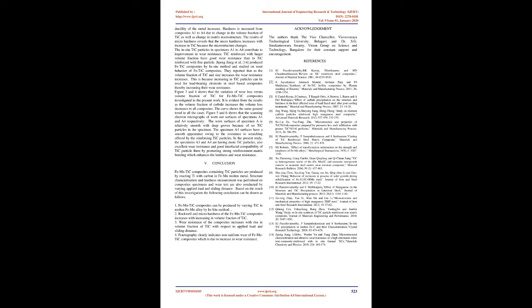In the present study, the specimens A3 and A4 have more TiC particles, also excellent wear resistance and good interfacial compatibility of TiC particles, thereby promoting strong reinforcement-matrix bonding which enhances the hardness and wear resistance. Conclusion. Fe-Mn-TiC composites containing TiC particles are produced by reacting Ti with carbon in Fe-Mn molten metal. Structure characterization and hardness measurement were performed on composite specimens, and wear tests were also conducted by varying applied load and sliding distance. Based on the results of this investigation, the following conclusions can be drawn.